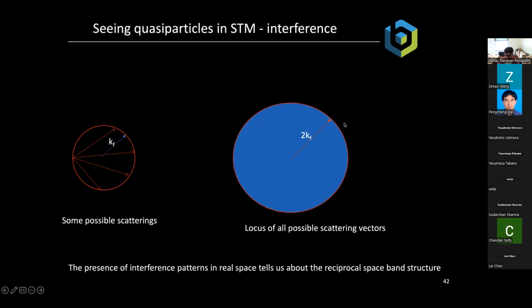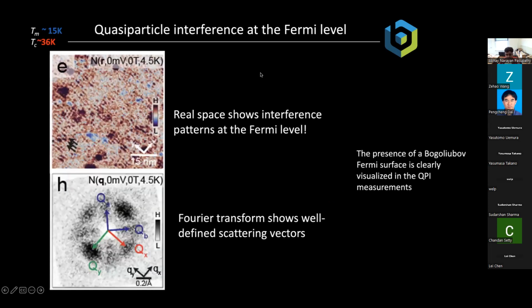And so generically, we measure patterns like this by looking at the Fourier transform of STM data. And the presence of these interference patterns in real space tells us about what the reciprocal space band structure of the material was. Okay, so now what we want to do is we want to do this same measurement at the Fermi level in our superconductor that has a pair density wave.